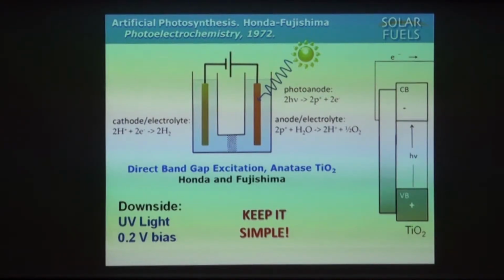TiO₂ is a paint pigment. It's in these walls in large amounts. It's very abundant. And what happens when it absorbs light is the band gap excitation produces a hole electron pair. And the hole is very strongly oxidized. It very quickly goes to the surface where it oxidizes water to something like a hydroxy radical. And that's the key to the success of the device.